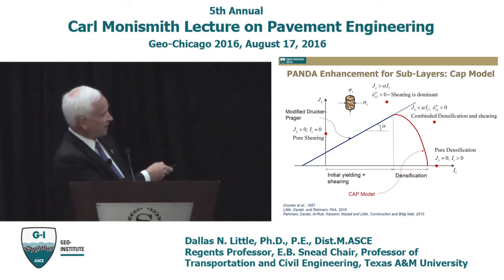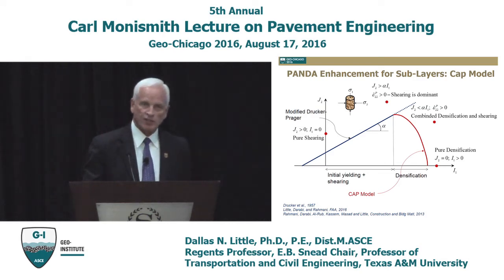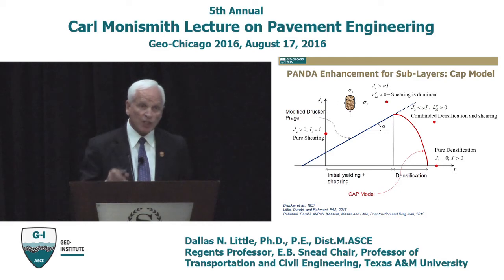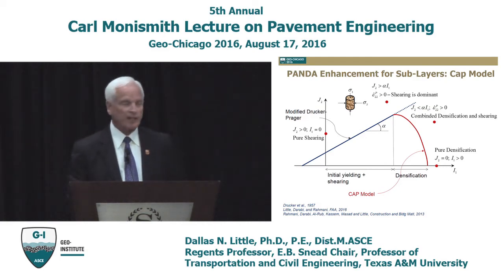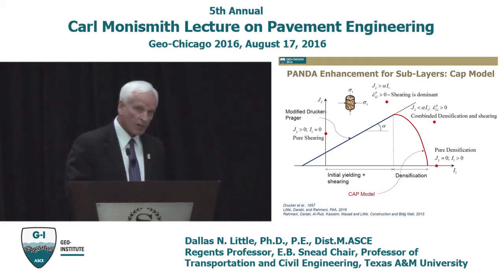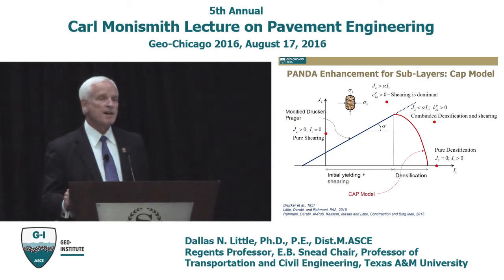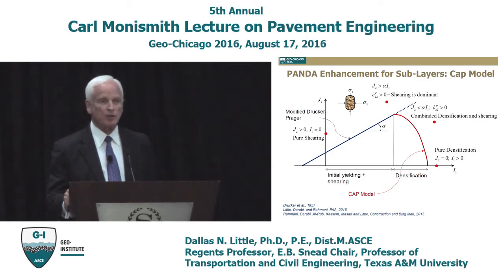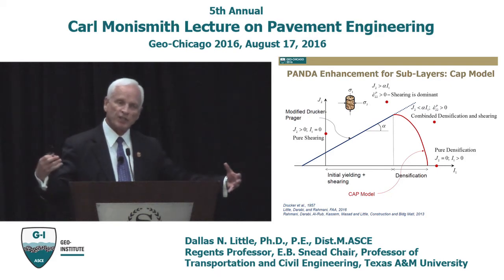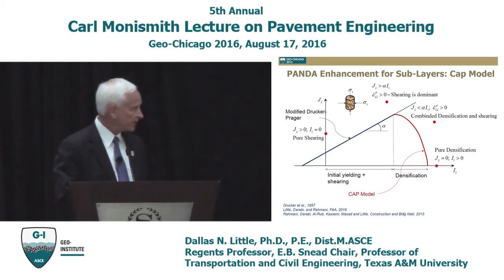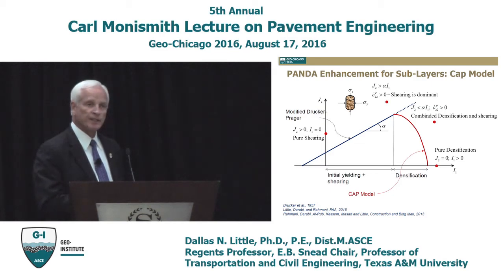And that tells us that even if we're below the shear surface, if we're outside of that red curve, densification can occur. And looking at the data at the test site there in New Jersey, we found that much of the time it wasn't the shear stresses that caused that densification, but it was indeed the consolidation, the confinement that occurred in the subgrade that caused that densification.